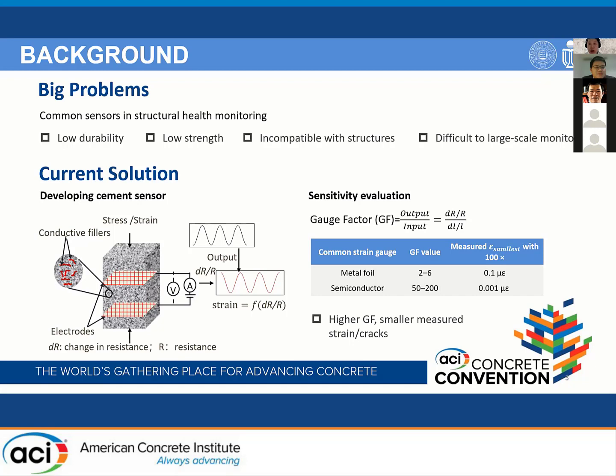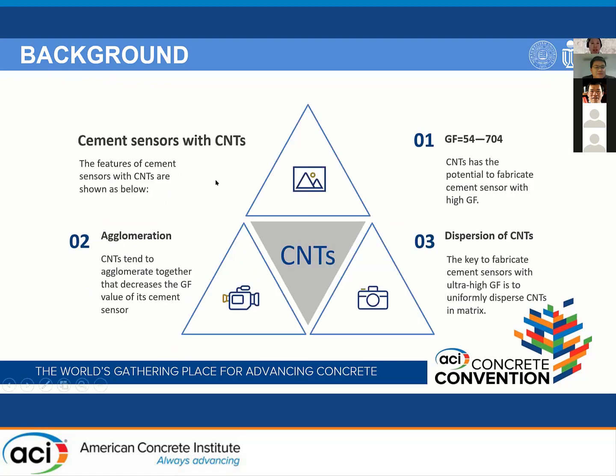Therefore, in order to measure the strain or cracks at the micro level, we have to develop cement sensors with an ultra-high gauge factor. It is believed that a cement sensor with carbon nanotubes has the potential to get an ultra-high gauge factor. And it is reported that the gauge factor of cement sensors with carbon nanotubes ranges from 54 to 704 in the literature, and this wide range is caused by the agglomeration of carbon nanotubes. As we know, agglomeration is a big issue for carbon nanotube composites, and it significantly hinders the increase of the gauge factor of this type of cement sensor.